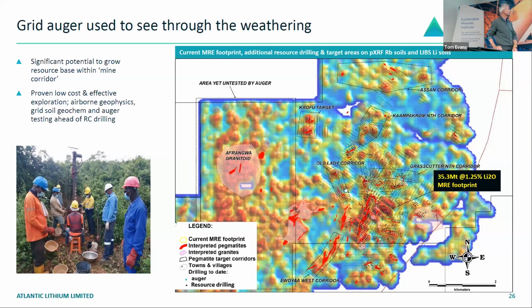The village elders and the traditional leaders are really pleased that we're employing a lot of the youth in that regard. But you can see here, the image below is a combination of rubidium and lithium in soils. And then in red are the mapped pegmatites to date, the current resource footprint predominantly in this area. And then the larger black dots are our resource drilling. So we've drilled 150,000 meters to date in roughly 800 holes. And then these finer dots here are all individual auger holes.